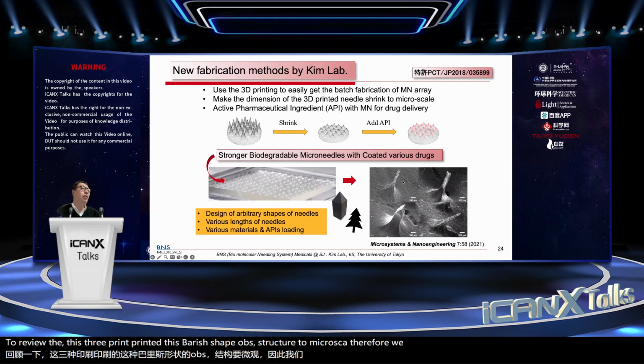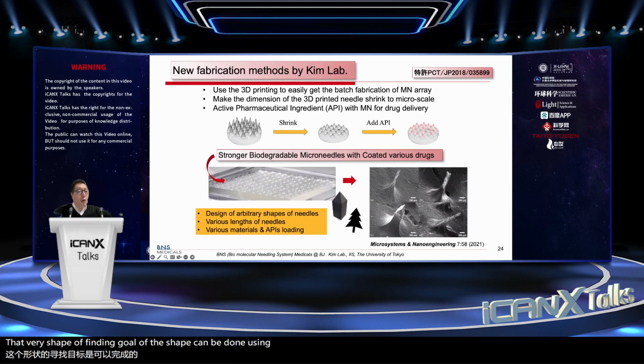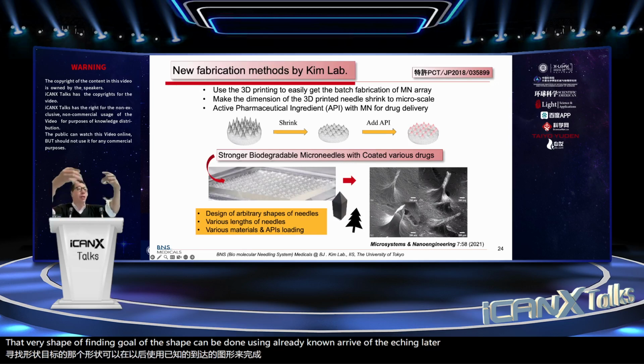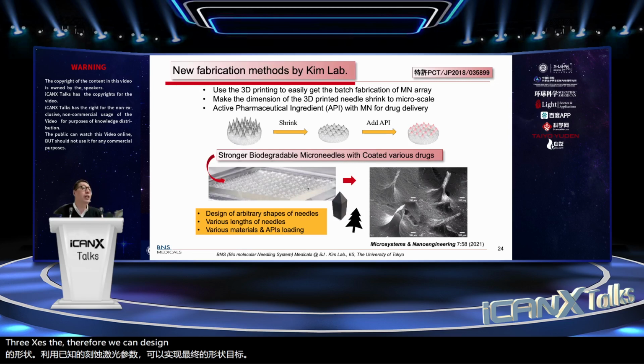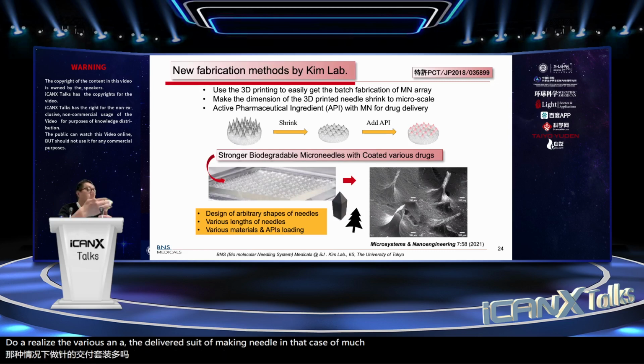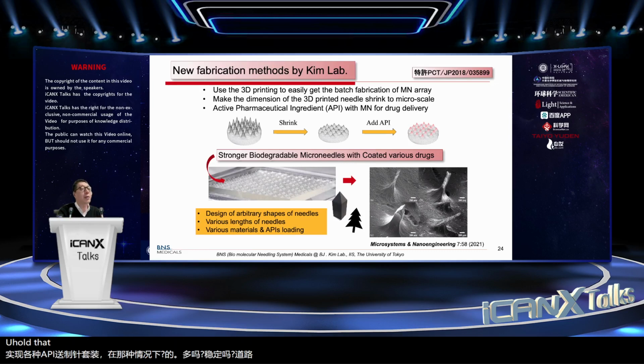Therefore, we designed the barrel shape. The final goal shape can be achieved using already known etching parameters in 3 axis directions. Therefore, we can design it in the 3D printer and print it at not micro scale but sub-milli scale, then etch uniformly, and finally the API can be coated. So actually, to realize delivering various APIs with this kind of microneedle in a much more stable way that conserves the activity of the API, coating is also available. So that kind of way we are also considering.